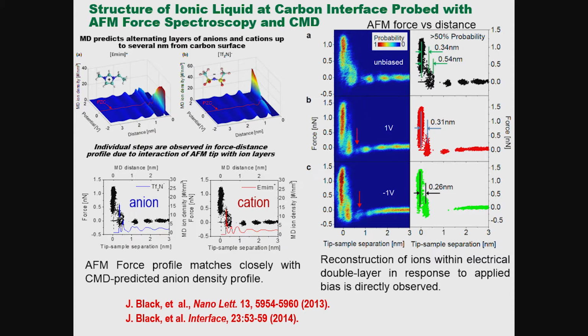We're also able to probe that interfacial structure using atomic force microscopy, as Jeremy talked about yesterday. Pushing a probe tip towards the surface and measuring the force on the probe tip as it pushes through ion layers approaching the surface. So here's the open circuit, or the zero point of charge structure, of this EMI-TFSI at the interface of graphene.